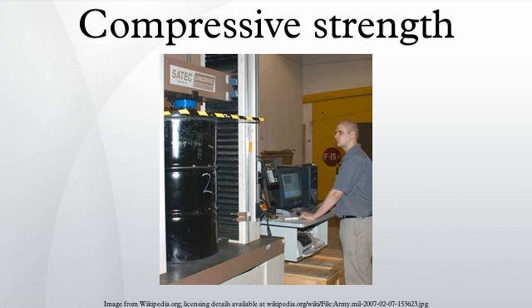As a final note, it should be mentioned that the frictional force mentioned in the second point is not constant for the entire cross-section of the specimen. It varies from a minimum at the center to a maximum at the edges. Due to this, a phenomenon known as barreling occurs where the specimen attains a barrel shape.